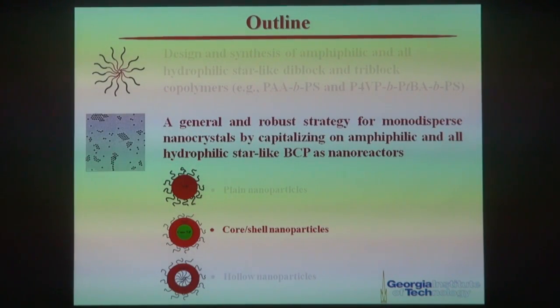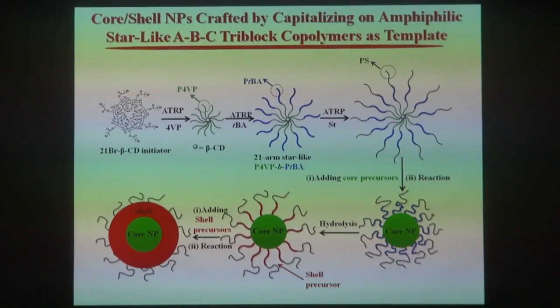Now I want to move on to talk about how this particular nanoreactor approach can also allow you to make a large variety of coaxial nanoparticles. We know that making a coaxial nanoparticle, as I will discuss later on, is quite challenging by conventional means. However, we use this star-like triblock polymer composed of innermost hydrophilic poly(4-vinylpyridine) in green, intermediate hydrophobic poly(tert-butyl acrylate) in blue, and outermost hydrophobic polystyrene in black. We can make a coaxial nanoparticle permanently capped by polystyrene.